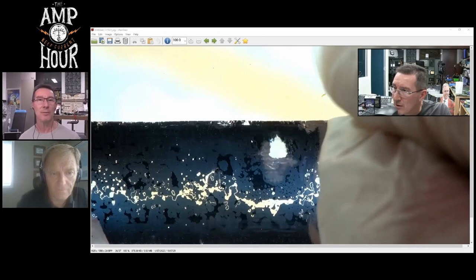Are there qualified parts that would be better for moisture ingress? Do you sell, for example, higher quality ones that are better? Like, we guarantee these ones are hermetically sealed and you won't get moisture in. Well, we don't have hermetically sealed films from what I know. I don't know that there are any. Well, I almost take that back. There are films in cans, so they're hermetic, but they're a much different application. But I think in reality, some of the progress that's been made on the encapsulants could get you such a near hermetic case that you would never experience this.